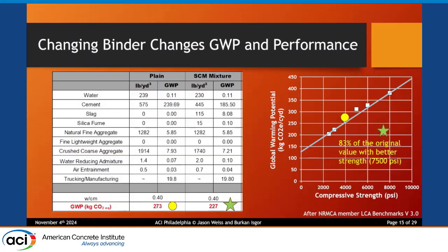So one thing we could do is we could go through and we could actually take out cement and we could replace it with slag and silica fume, right? And we could reduce our global warming potential. We could go from 273 to 227. We have now moved to the green star. Well, that's awesome, right? We dropped it down, all right? We had that magical line that's down here. That's great. But at the same time, we accidentally improved in performance, right? So there's probably more we could do here if we really want to reduce the global warming potential by moving this, all right, back over.